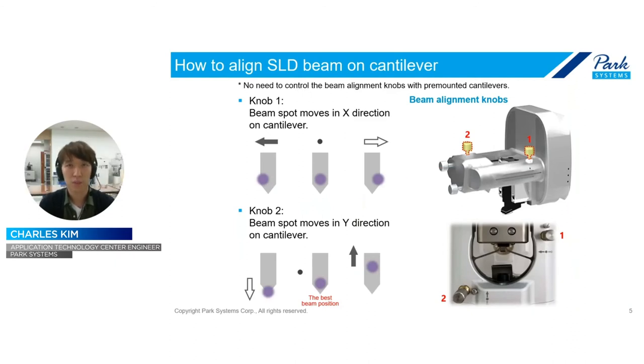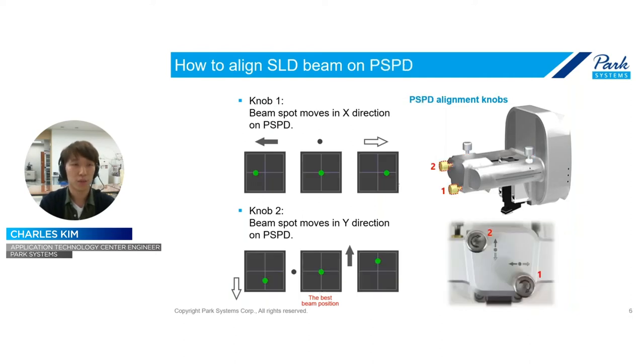After that, the AFM system is using the SLD, which is a kind of laser, to detect the cantilever motion. So you need to align the laser on the top of the cantilever, but if you use the Park AFM probe, then you don't need to control the beam alignment, because every time the cantilever is pre-aligned at the center of the vision. But when you use a cantilever not mounted by Park Systems, then you need to do this kind of job to align the laser. And after aligning the laser on the cantilever, you need to align the laser on the position sensitive detector like this again. Then the cantilever preparation is done.